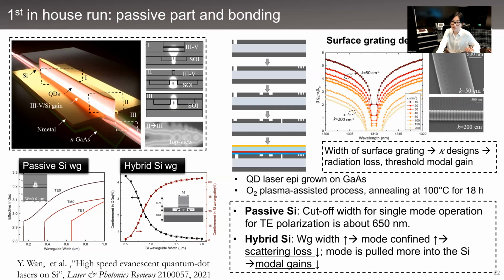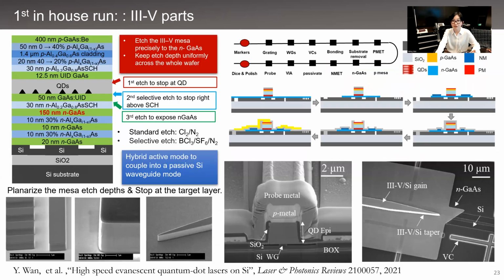And for the surface grating that is formed on top of the silicon waveguide, the width of the grating can be tailored to achieve different coupling designs, and thus different radiation loss and threshold modal gain for the lasers. So for our optimized design, a narrow width of 50 nanometer was chosen, which corresponds to a calculated coupling coefficient of roughly 50.